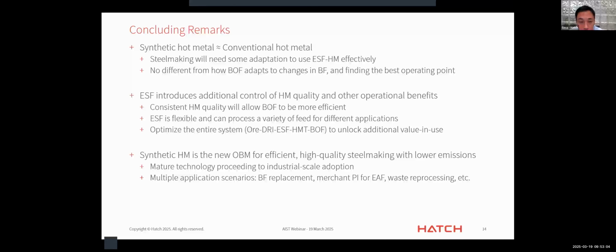But the main benefit of using ESF hot metal from an operation perspective, in addition to the quality, cost and emissions, is the consistency of that hot metal quality. It comes from the very powerful ability to carefully and rapidly control the operation inside the ESF, and separating the DRI process into an upstream process does not impact hot metal quality directly in operation. It is a very flexible process, can be designed for a variety of feed to provide a very wide range of hot metal specifications, and allows you the opportunity to fully optimize your value chain from ore to DRI to ESF, with possible pretreatment and your steelmaking operation, to unlock all the values and maximize the value in use. It's a very mature technology.